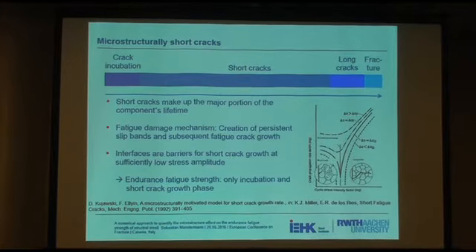And for the endurance fatigue strength, we observe that the incubation phase and the short crack growth phase are completely run through, but there is no transition to long crack growth. Okay, in other words, if you load a sample in the region of the endurance fatigue strength, you will see a lot of cracks inside, but they are very, very short.